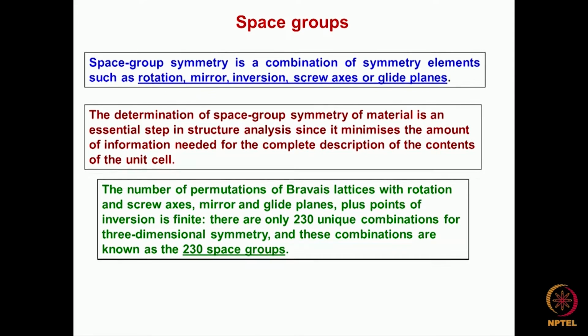Having looked at these 32 point groups and how they are represented in a stereogram, if you try to generate a space group, what we have to do is this: a point group is around a point which we are considering. Space group means that around the lattice, if we put motifs having these point groups around each of them, what are the distinct types of crystals which could be generated with specific symmetries associated with them? Here again, many combinations are possible. Distinctly, finally we find that 230 space groups are possible.